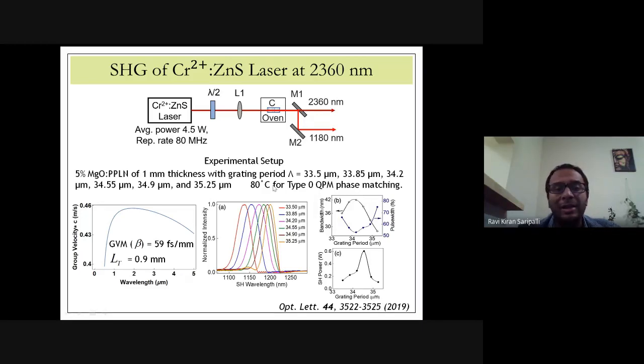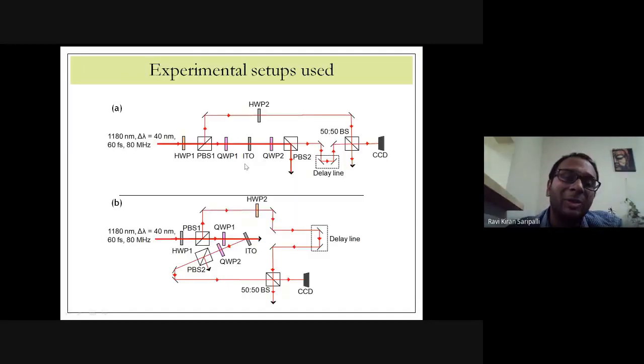and we had a little bit of tunability from 1180 to all the way to 1200 nanometer. And this work is still in progress. More details of this can be found in our publication recently. So these were the experimental setups that were used.